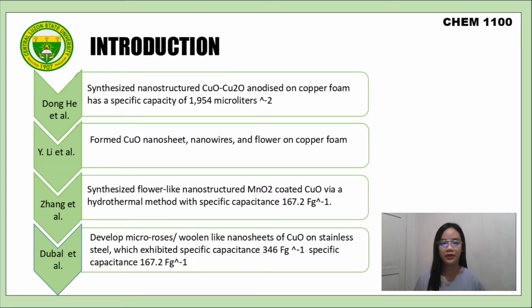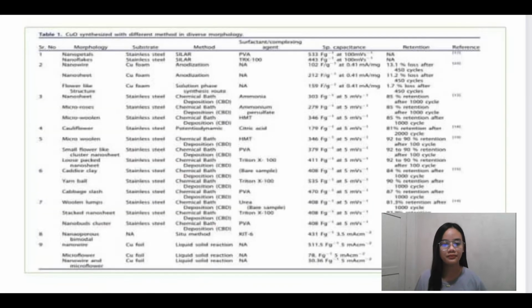In another experiment, they reported nanostructured CuO with different morphologies, woolen clump, stacked nanosheet, and nanobuds, developed on stainless steel by chemical deposition method with surfactant. The 3D framed nanostructure of nanobuds of CuO demonstrated a specific capacitance of 346 F/g, higher than the other morphologies. Next slide, please. In here, we can see Table 1.